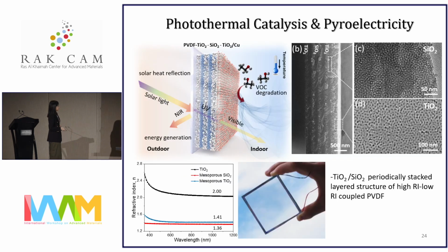So here we have TiO2 silica. Instead of a core-shell structure, now we have periodically stacked them, as you can see in the layer architecture in the SEM picture here. And they are mesoporous in nature in the TEM images and SEM images here. They are layered structures with high refractive index alternating with low refractive index, and they are coupled with ferroelectric material to enable multifunction: VOC degradation, solar heat reflection, as well as energy